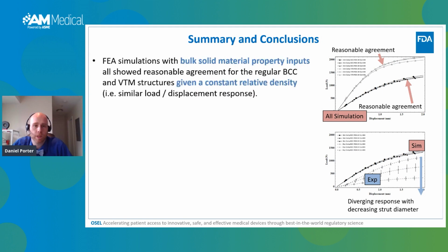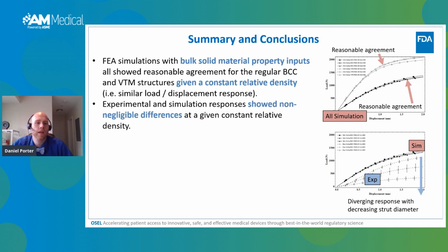The FEA simulation with bulk solid material property inputs all showed reasonable agreement for the regular BCC and generally for the VTM structures, given a constant relative density, when taking into account what we're testing, which is the reaction load and displacement response. And that's shown in the graph in the top right. So you see the simulations all line up and perform the same, even when you adjust the strut diameter. Experimental results, though, showed a non-negligible difference between experiment and simulation response at a given constant relative density.